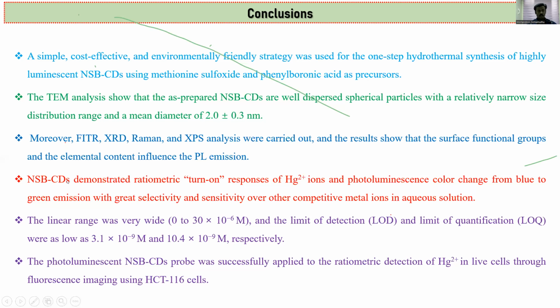The boron doped carbon dot also demonstrated a ratiometric response to mercury ions, with the photoluminescence color changing to green emission, with great selectivity and great sensitivity over other metal ions. The wide linear range is from 0 to 30 micromolar, and the limit of detection and the limit of quantification are also in the nanomolar range. Finally, the boron doped carbon dot was successfully applied to the ratiometric detection of mercury in fluorescence imaging applications using cells. This paper I also published in Analytical Methods 2 months ago.